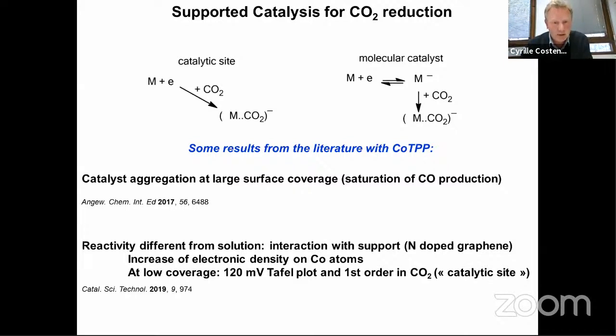And so now, if you run catalysis, you have a very different situation from the one you had with the catalyst away from the electrode, because you cannot make the reduced form of the catalyst. You have a direct binding of the substrate onto the catalyst as you reduce the cobalt. And this is observed experimentally by the fact that now you observe a 120 millivolt slope, which is first order in CO2. So now your molecular catalyst behaves exactly as a catalytic site as you would have with a metallic electrode. And so now you have a bridge between molecular catalysis and electrocatalysis. And so the analysis I showed previously for molecular catalysis is no longer valid in that case, and you have to work out the analysis in a different way.